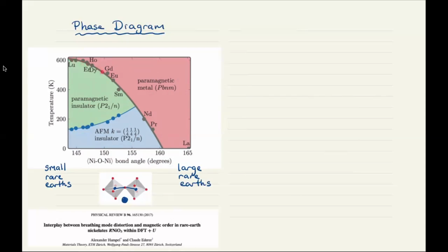It's this region of the phase diagram, where the transition goes directly from a metal to an insulator without any magnetic ordering, that's usually assigned to be the Mott transition. The region of the transition between the paramagnetic metal and the antiferromagnetic insulator, one could argue, is just a conventional magnetic transition that's accompanied by the transition to insulating behavior.